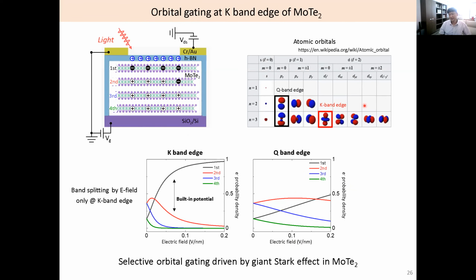And then, as I said, the K point, MoS2 and MoTe2, they are called group 6 TMD materials. They are cousins, relatives, similar materials. So depending on the momentum of electrons in the conduction and valence band K band edges, we have this split of energy state. So here, if we make this MoTe2, 4 layers of MoTe2 are drawn here, and we have a top hBN layer, okay? And so this is a tunneling device as well.